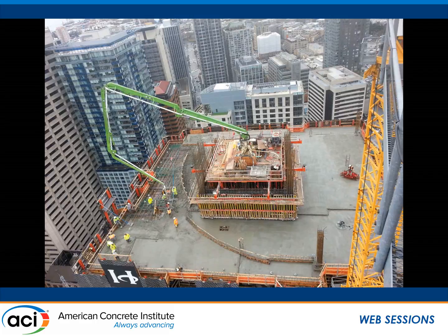They made this kind of interesting story on this level right about here. They were pouring the concrete, and they used the same formwork system and shoring that they did for the 7.5-inch slab. In this area right here, the thickness of the concrete was about 24 inches. They called me and told me that one of the forms kind of bulged out, and they had to patch it last minute. So we got a little bit of extra concrete in the beam here. It looked like a V shape. After analyzing the beam, it turned out to have more stiffness because it's deeper at the midsection, so it was even better.